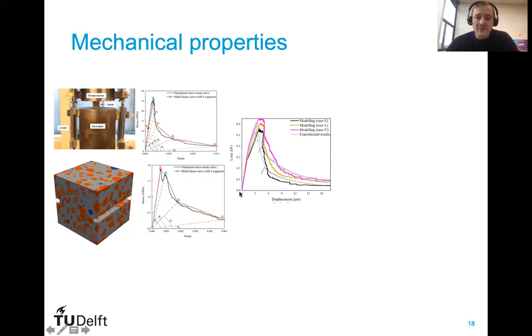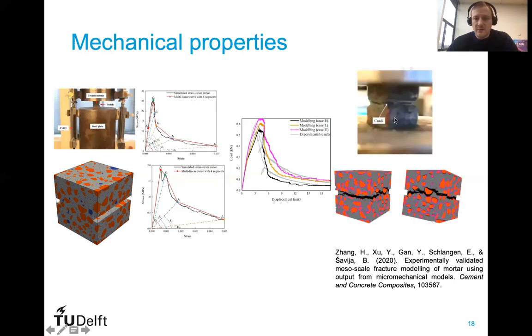And we have an excellent match between the experiments, shown here in gray, and the modeling results, shown here for different cases. I will not go into detail, but we tested different scenarios. We have an excellent match between the modeling and the experiments. And also in terms of crack path, this is how a crack looks in the experiment, where we have a tortuous crack path coming from the notch. And the same thing in our simulations, where we have cracks going around the aggregates, of course, because the interfaces are the weakest links, but also getting a tortuous crack similar to the experiments.